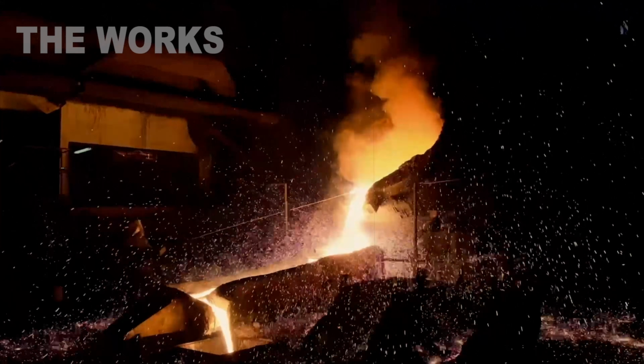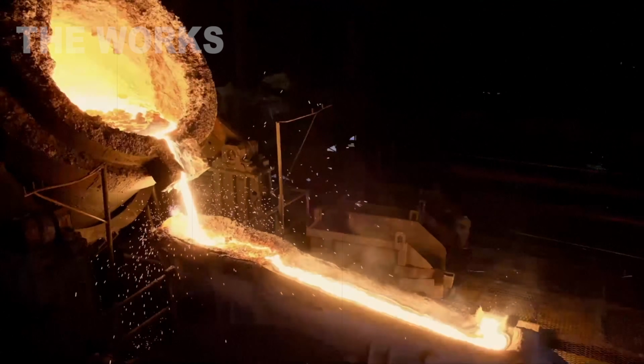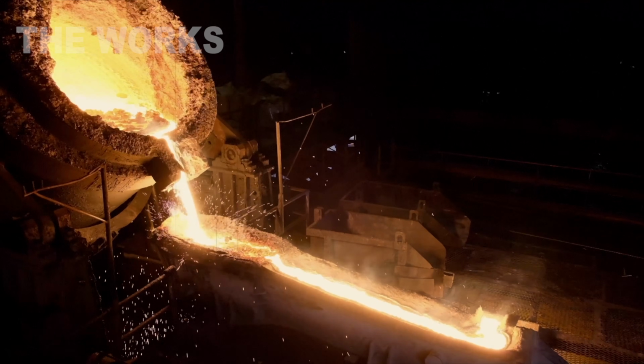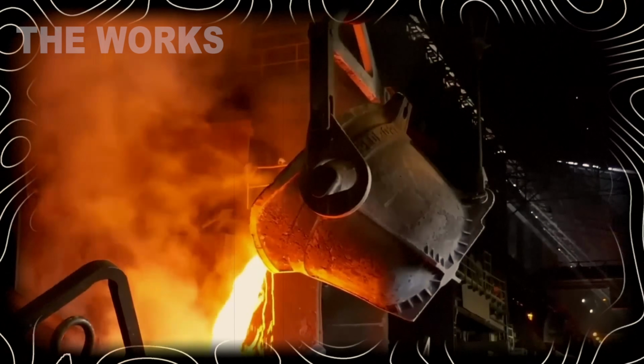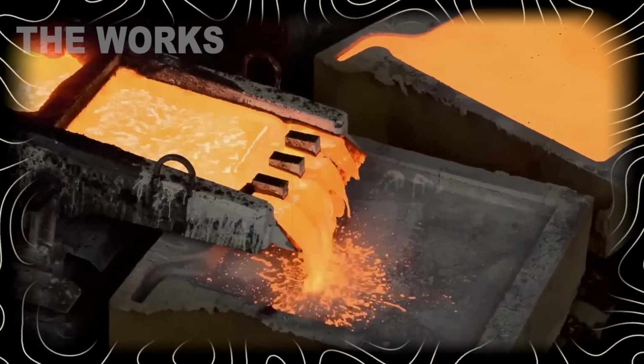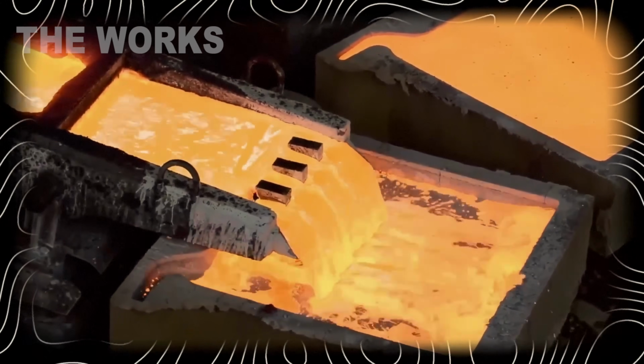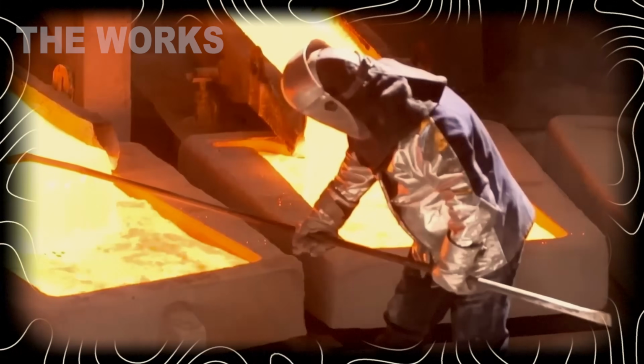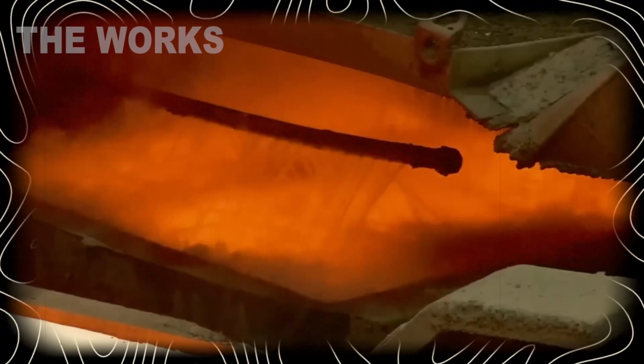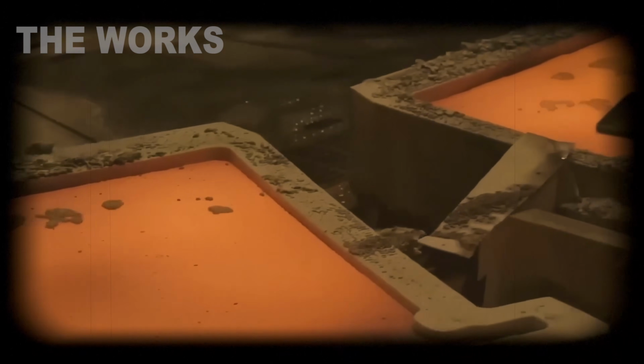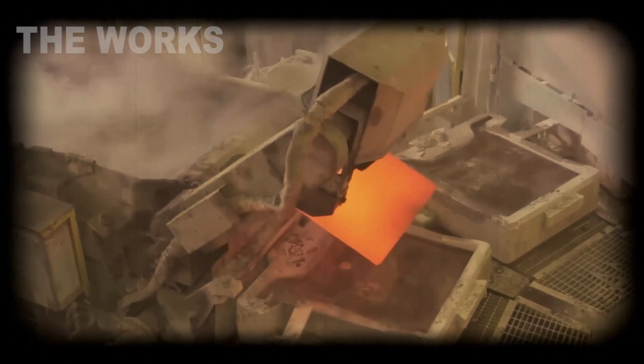The matte is poured into a converter. Pure oxygen is blasted in under pressure. Remaining iron and sulfur burn away. Temperature climbs to 2370 from the exothermic reaction. After 6 hours of blowing, what's left in the converter is blister copper, 98% pure. But that's not enough for wires, you need electrolysis.